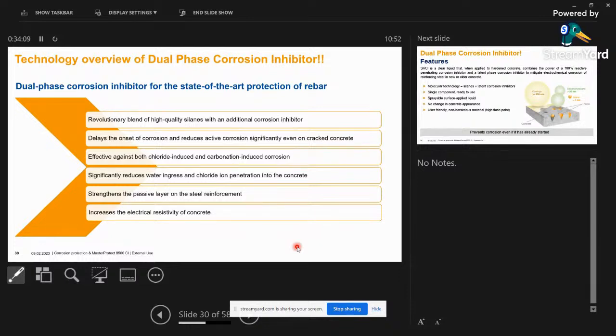Just to give you an idea, when you combine silane you get siloxane, which is slightly larger in size, therefore its penetration is limited. When you combine a lot of siloxane, what you get is a silicone based coating, which doesn't have the penetration, it's more of a film. So when you move towards the silicone side, it becomes a film. Siloxane, just below silicone, is not a deeply penetrative material; rather you can call it a surface sealer. But when we talk about silane, it's a truly deeply penetrative material of all the impregnators that could possibly be thought of. So that's one benefit of it.